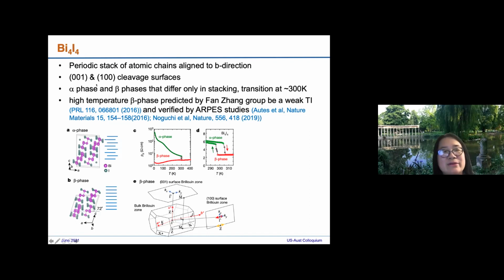It turns out they have two phases, an alpha phase and a beta phase. They differ only in stacking, and there's a phase transition right around room temperature. Here's data, I think from Nature Materials. The alpha phase is the low temperature phase. The beta phase is the high temperature phase, but presumably you can obtain the beta phase at low temperature if you quench the material: you heat it up to 350 Kelvin and rapidly quench it.